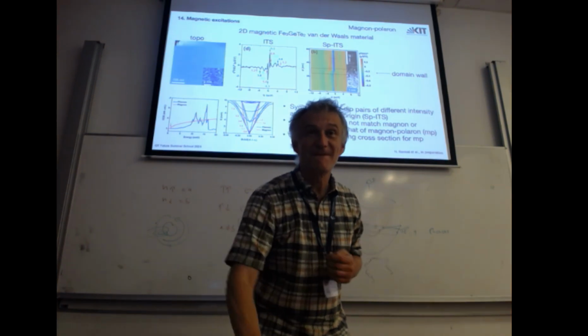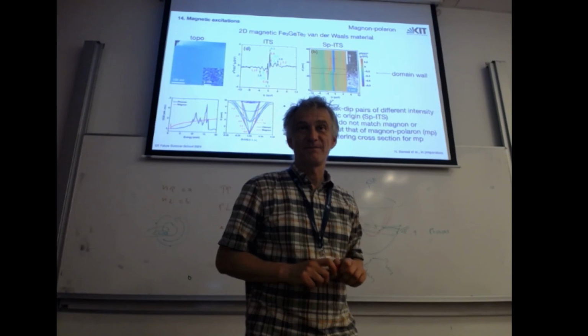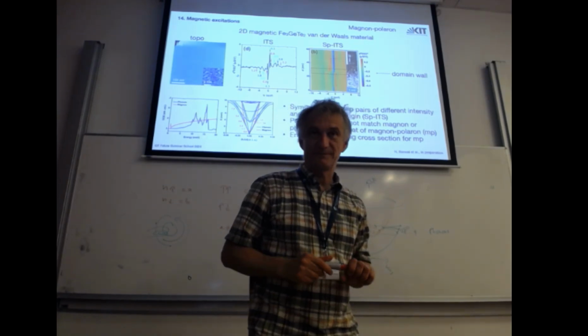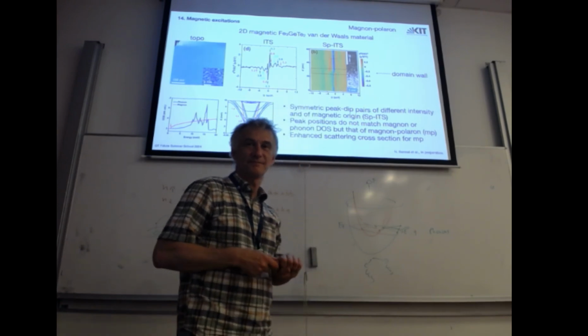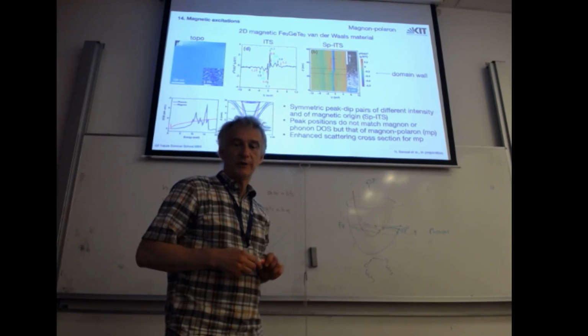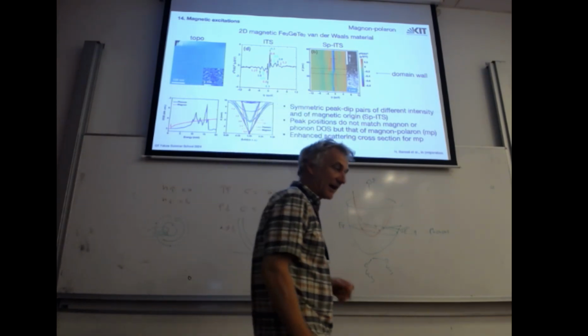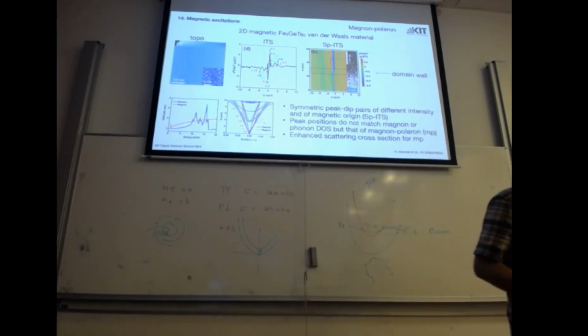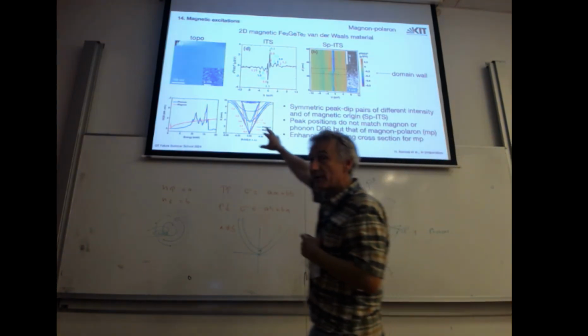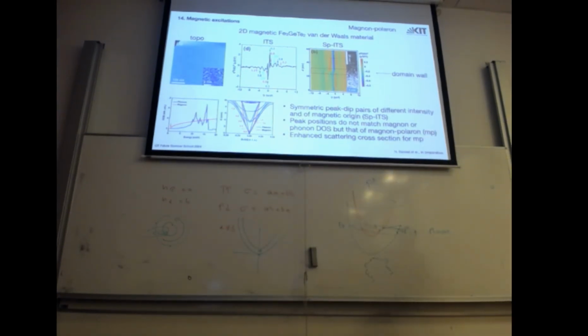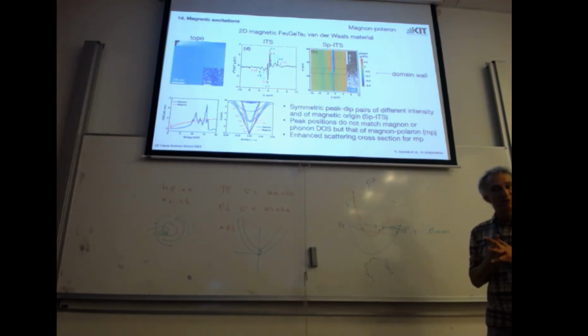Yeah. Why can't it just be a composite process where I first emit some phonon which allows me to dissipate some energy elsewhere and then create? Yes, you can also think of that image, and I would do the same, but at the same time. You say I create a magnon and a phonon, then we would have a very complicated construction, but maybe possible. But we see these peaks only where the dispersions cross, and that means magnon and phonon have the same Q and the same energy, then it's hard to say what is the magnon and what is the phonon.